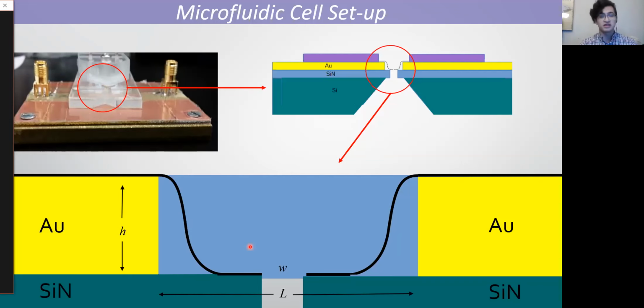However, now we've transitioned more to dielectric breakdown, where instead we use varying volt pulses to induce the break in the graphene sheet. This can be done by our computer, and we set specific voltage ranges to make sure that we don't go overboard and we construct the ideal graphene nanogap. After the nanogap is created, we run our IV characteristics, we measure its resistance. Via that, we can double check to see the size that we got and if everything goes according to plan. For a few beginning setups, we can also see optically to test if we have the gap. If everything is secure, we can now flush our microfluidic cell with the DNA and proceed with the translocation.